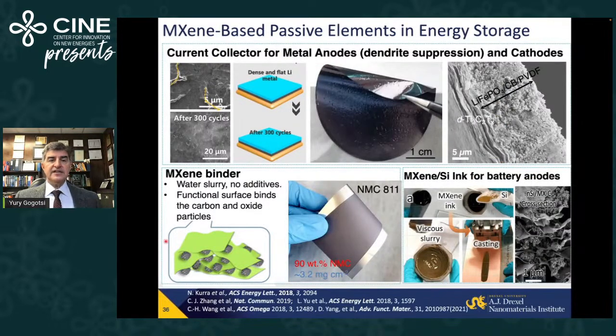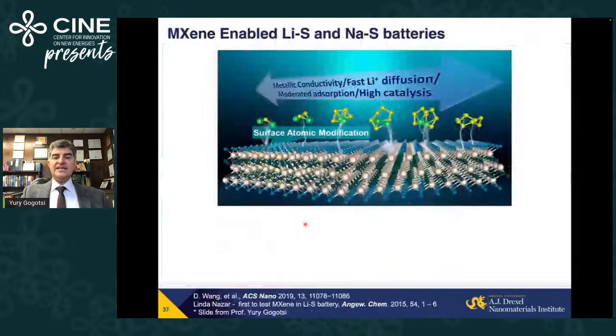And as a result, it's possible to use it for electrodes, current collectors of metal batteries, not only metal ion batteries. You can make much thinner current collectors compared to copper or aluminum for cathodes and anodes of batteries. One can use it as binder instead of graphite and carbon nanotube for silicon or NMC or carbon. So I think you get the idea.